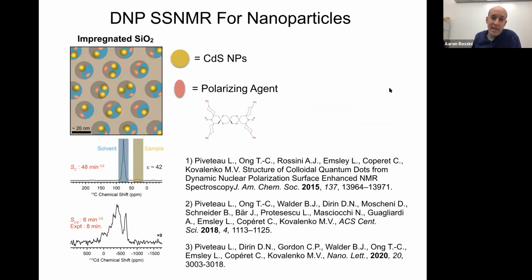There's been a lot of work done by conventional solid-state NMR to look at nanoparticles. I'm going to skip over that for the sake of time and just focus on the DNP. In 2015, when I was a postdoc with Emsley's group, we did this nice study in collaboration with Maxim Kovalenko and Christophe Copéret, where we came up with a way to do DNP on semiconductor nanoparticles. You take your semiconductor nanoparticles, which you usually have as a stable colloidal solution in an organic solvent, you trap the nanoparticles in mesoporous silica, and you add your polarizing agent. The reason we do this is because the nanoparticles and the polarizing agent then become trapped in the pores of the silica together.